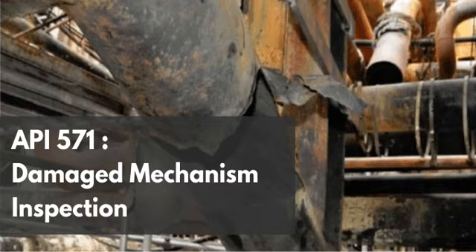It all ties back directly to that chromium rule we just established. Percentage of chromium. Right. To get those incredible high-performance properties, particularly the amazing corrosion resistance, duplex alloys are heavily alloyed with chromium. Oh, okay. And by definition, a duplex stainless steel has a mixed microstructure. It is roughly 50% austenitic and 50% ferritic. And it's that ferritic half of the matrix that is the problem. Exactly. The austenitic phase is largely immune to this specific mechanism, but the ferritic phase is highly vulnerable.